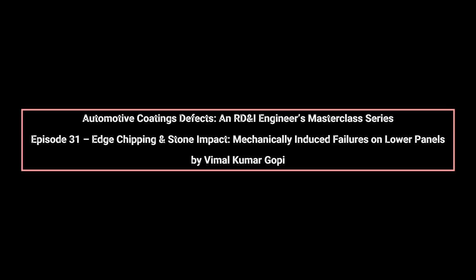OEM specifications carefully control total film thickness, balancing aesthetic requirements with mechanical durability. Thinner films may look glossy, but lack sufficient mass to absorb energy without cracking. Uneven film distribution along edges and corners, caused by spray pattern limitations or operator variation, creates stress concentrators where chips preferentially form. Overspraying to increase thickness is also detrimental because excessive build increases internal stress and brittleness, making the film more susceptible to impact-induced fracture.